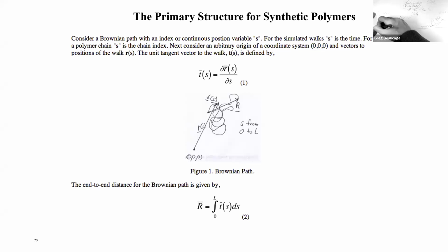So in this worm-like chain model, if you're going to do a computer simulation of chains and you want to determine the Kuhn length, the computer simulation is going to generate something like that. Or if you have DNA, a photograph of a molecule, or in scattering, you measure scattering, so you're plotting log intensity versus log Q. So you have the Gaussian part with a slope of -2, and then it goes to -1.